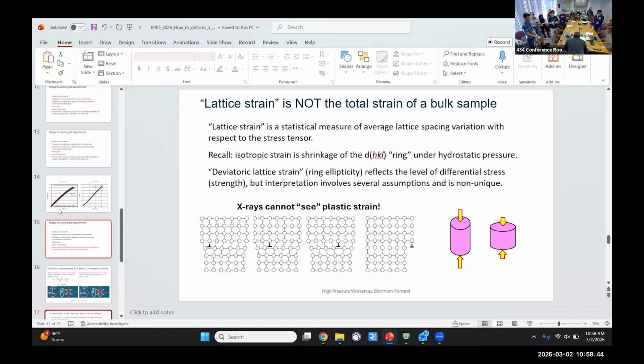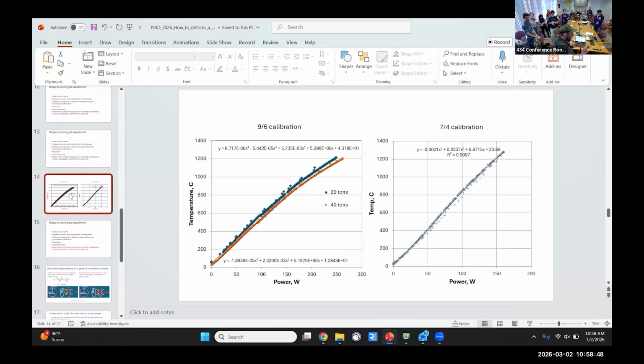And then I think the last thing I should mention is that once it's under high pressure, we also want to heat it up. So like I said, you connect cables to the outside of this thing and you run a current through it. When this is closed and you're actually pushing on it, you have an anvil on the top and an anvil underneath, and then we run a current through that. I'll use the tungsten carbide. Then a current through the anvil, which goes through our graphite furnace, which goes down through the anvil on the bottom to complete our circuit. And when we run a current through the furnace, it'll heat up, and we can heat it up to 1500 degrees, kind of no problem, and then deform our mineral.